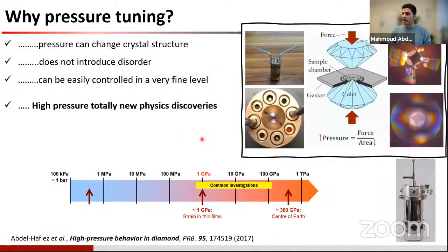Apart from crystal growth, we also have unique techniques that are very important for different kinds of materials: we can study materials under pressure. Pressure is a very clean tool, because you do not change the chemistry of your material, you change only the distance between ions. By changing the distance between ions or atoms, you induce new phases and so on. So you can go from insulator to superconductor and so on. That's the experiment on hydrogen. Hydrogen is a gas, and we try to make it a superconductor, or a room temperature superconductor.